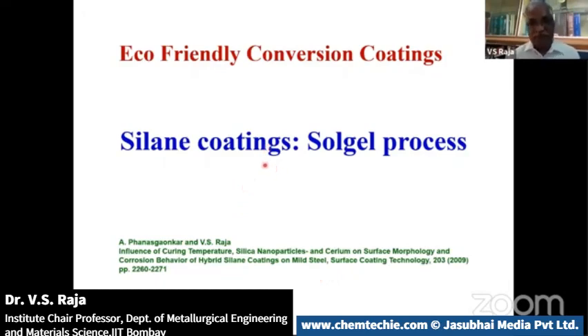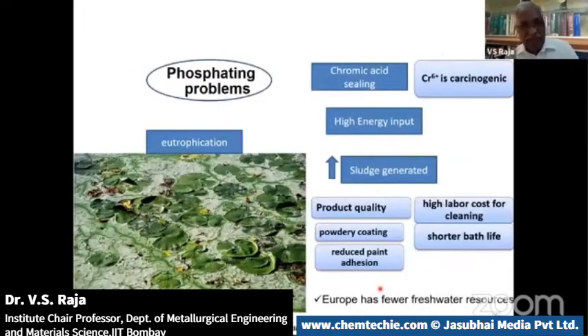So people talk about coatings based on silane. We have done this work, with Phanasgaonkar, a postdoc candidate in our place. It's an eco-friendly coating, simply silane, silica. Silica is as friendly as possible, because you have a lot of sand, so it's environmentally friendly. Of course, you need to modify it with various ingredients you add to it. Now, what I was talking about is that in Europe, for example, phosphate is now banned, not only chromate, because phosphate is a good nutrient for plants. So eutrophication is a problem for fresh water resources. That means the challenges grow as technology becomes more developed and resources shrink, and there is a lot of legislation to not use the normal coatings.